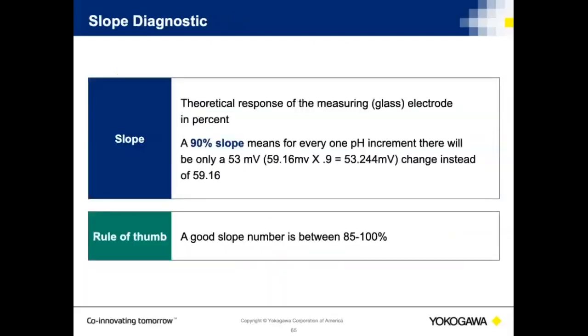Key diagnostics. Slope. Slope looks at, and we saw that line before, we showed it. What it's doing is telling me the output of the electrode has changed as that measuring electrode changes. As you can see in the illustration, going from 59.16 millivolt output to 53.244, that's all right. It's still a good slope. It's a good slope value all the way down to about 85%. So the rule of thumb is a good slope is going to be between 85 and 100%, day in, day out.